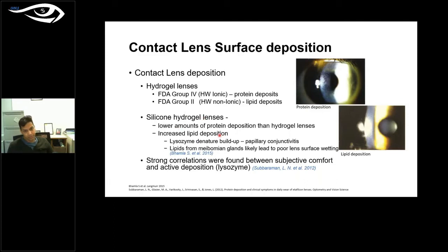Silicone hydrogel lenses, on the other hand, are reported to have lower amounts of protein deposition than hydrogel lenses, and this is partly because of the material nature. And also we discussed that hydrophobic surfaces on silicone material generally attract more lipid deposition. One of the deposits which is famously seen in relation to silicone hydrogel lens is lysozyme. And this denatures and then builds up on the lens surface. This is an important deposition because when it happens on the lens surface, it actually triggers an immunological response on the eye, and it can eventually lead to papillary conjunctivitis also.